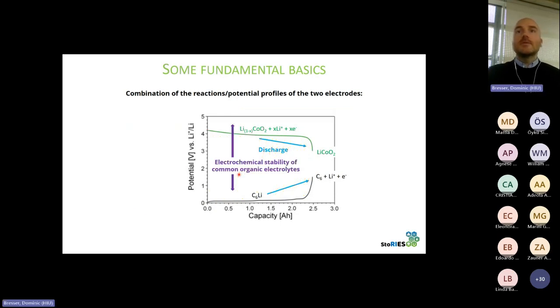There was one big issue towards the development of lithium-ion batteries, though: the electrochemical stability of common organic electrolytes is somehow limited, maybe not towards oxidation, or towards high potentials, but towards reduction, basically. So you see there is a little gap here to graphite. And in fact, this was one of the biggest issues, one of the greater challenges probably towards the developments.